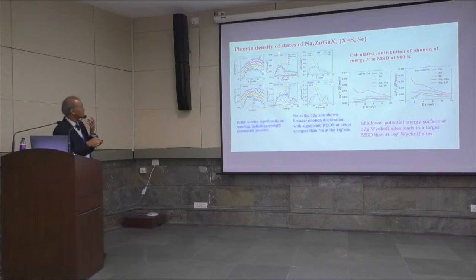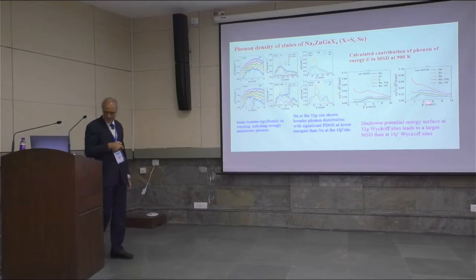What we identified here is that the key phonons where the significant broadening takes place are associated with the sodium atoms at the 32 G site, what they call sodium 1 and 2. So that has a large broadened structure, whereas the other one has a very sharp structure. And then these are calculations of the mean square displacements, which tell us that the sodium at the 32 G site has a large component at this low energy.